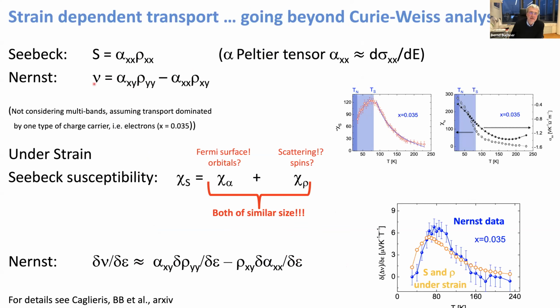So when you write down the Seebeck effect, you take this Mott formula. You can write it up in the following form: it's a product of the so-called Peltier tensor times the resistivity. And here I assume a single band, so I forgot about all these complications due to multi-band effects.